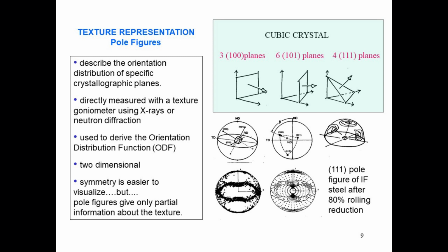And if you have now many points, you can represent the density of points using intensity lines, much the same as we do with the weather maps that represent temperature or winds. So these lines are lines of equal intensity, meaning that this is the volume fraction of material represented by this intensity line. So this is a typical rolling texture. As you can see, I'm plotting here these 1, 0, 0 planes, but now in this texture we have 500 orientations, so there are 1500 points here.